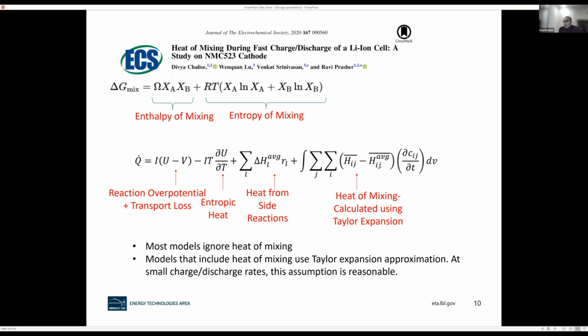Most of the models ignore the heat of mixing. And the models that try to include the heat of mixing assume the concentration gradient is very, very small, so they use a Taylor series expansion. But as I showed you earlier, even at 1C, there is a huge concentration gradient. So we cannot ignore heat of mixing.